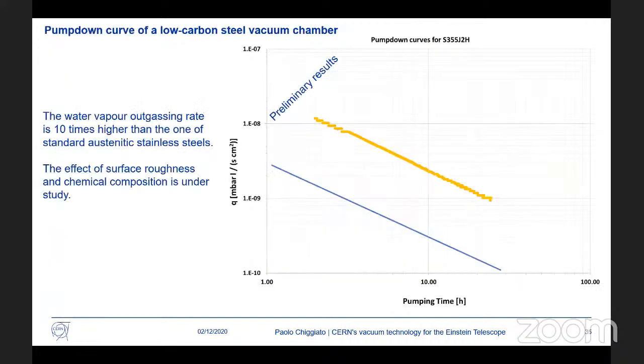Unfortunately, there are always some drawbacks, because the situation would be too beautiful. Certainly there's something wrong, as is usual, and this is the case for the water pumping. In fact, this material is, as you know very well, prone to heavy oxidation, and we expect for that a rougher surface than the one for austenitic stainless steel.